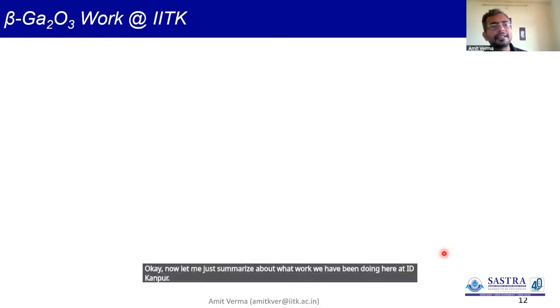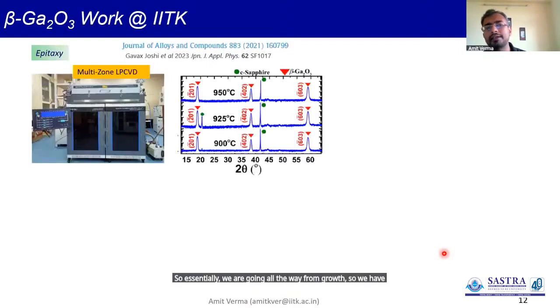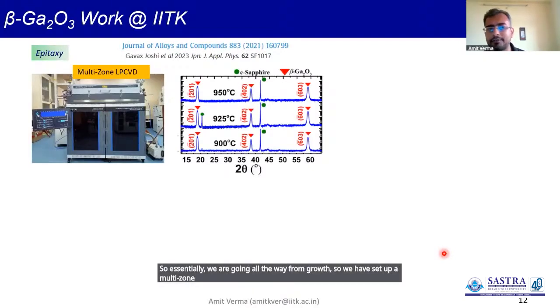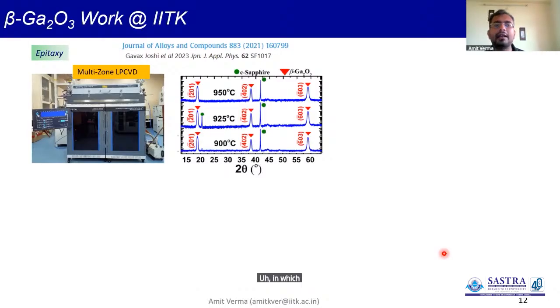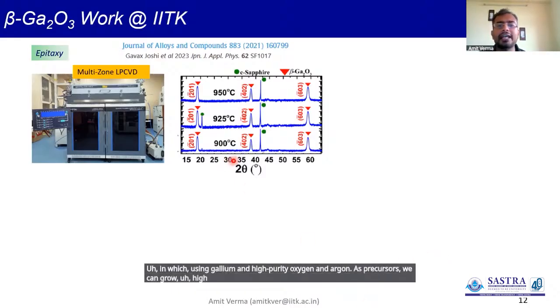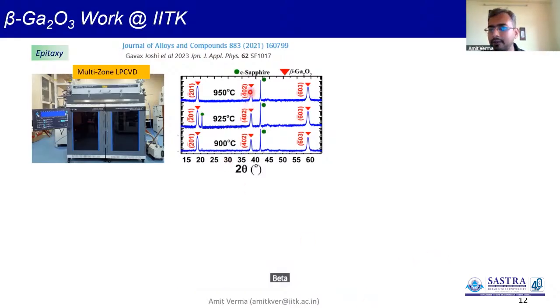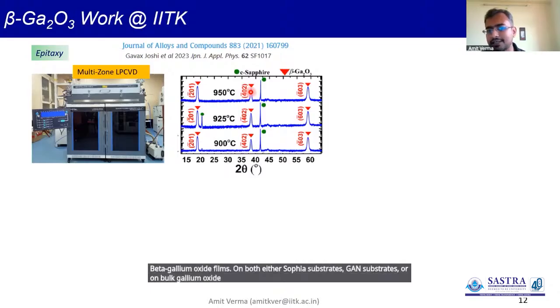Now let me just summarize what work we have been doing here at IIT Kanpur. So essentially, we are going all the way from growth. We have set up a multi-zone low pressure chemical vapor deposition system, in which, using gallium and high purity oxygen and argon as precursors, we can grow high quality epitaxial beta gallium oxide films on either sapphire substrates, GaN substrates, or on bulk gallium oxide substrates.